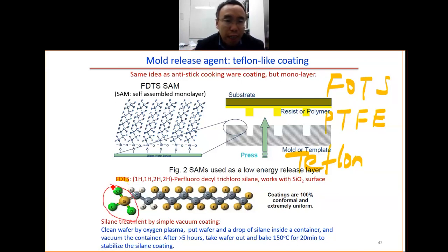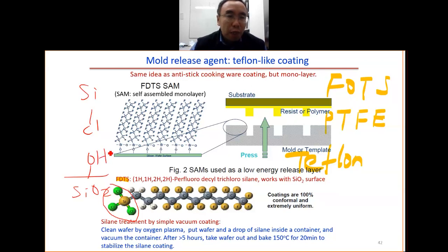So trichlorosilane. We have one silicon, and we have the chlorine. For the wafer, silicon oxide, for instance, it's not hard to have the surface terminated by the hydroxyl group. So you do the oxygen plasma. You clean the wafer, you do oxygen plasma, then you have this hydroxyl group. You leave it in the air for some time, you get this hydroxyl group. So what will happen? When you put this silane on top of this wafer, there will be a chemical reaction.